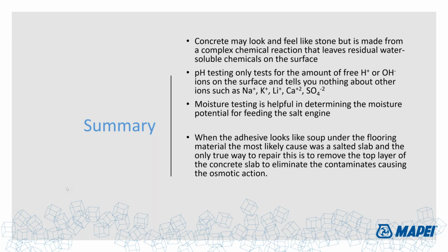You've got to wonder, how is that even possible? Well, in one case, that slab was highly burnished and had a little bit of fly ash in it, which kept it virtually non-porous on the surface. So if it's all non-porous, there's no evaporation rate and there's no MVER. But that means all the moisture is captured inside the slab, and that's why the RH levels are so high.